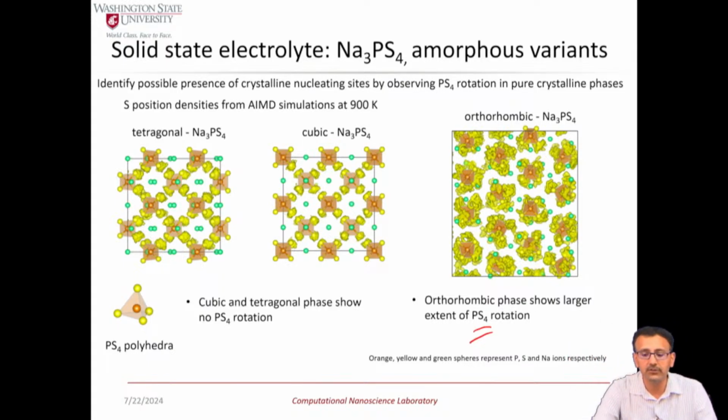And there is a theory based on the Anderson-Stuart model, which predicts the ionic conductivity as a function of the ion hop distance, the shear modulus, and something called a doorway radius. And the doorway radius becomes quite a bit higher when they are in the amorphous phase, and therefore that leads to enhanced ionic conductivity. I'll show you some results later of how it really works out for these structures.